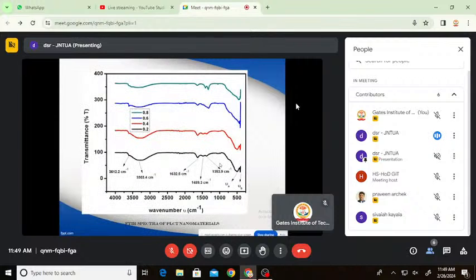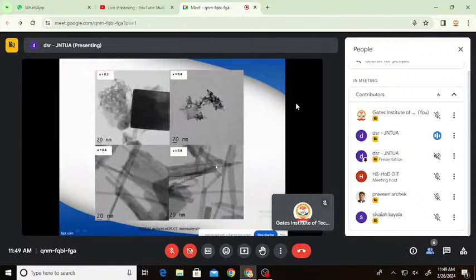This is the HRTEM images. Then from the TEM images, these nanofibers are even more clear. So from the images, it is evident that the partial formation of nanofibers started at z equal to 0.2 and ended with absolute formation of nanofibers at z equal to 0.8 content. For z equal to 0.2 to 0.4 compositions, unsystematically aligned spaghetti type nanofibers.